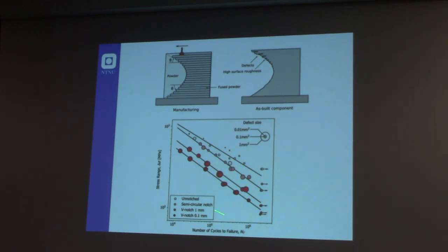We made different kinds of notch configuration, notch specimens: a semicircular notch, a V-notch with a notch radius of 1 millimeter, a V-notch with 0.1 millimeter, and we also plot the fatigue curves showing the size of the defects that we find in the component. So we are not only plotting the stress level, but for each curve we are also reporting the size of the defect that we find in the component. I think it is a nice representation.